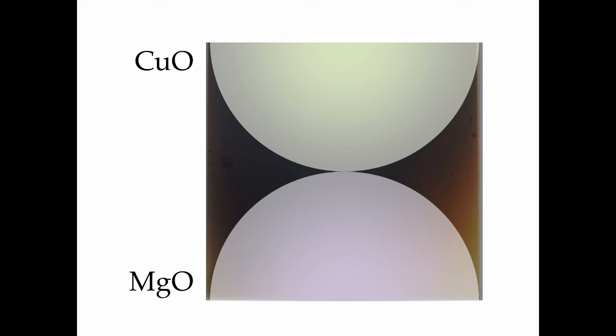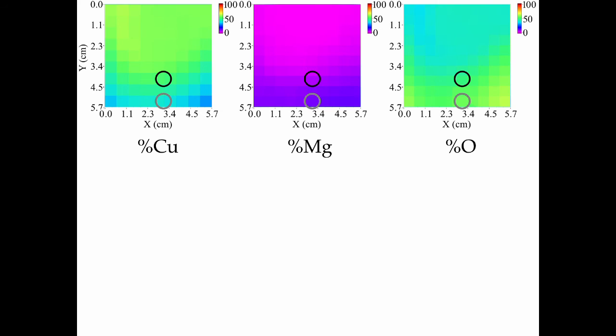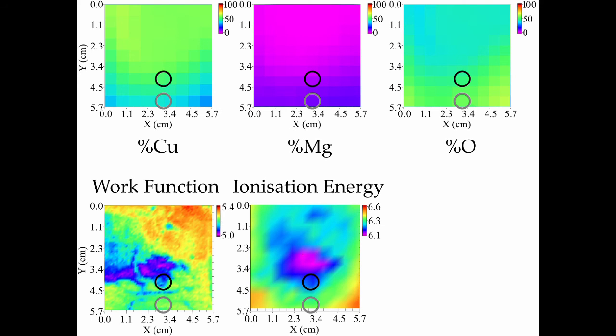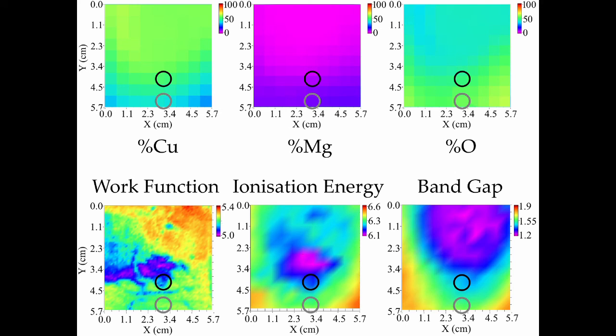To highlight the ability to tune the electronic properties of metal oxide compounds with a spatial variation in the chemical composition, and to demonstrate our analytical capabilities, we return to the copper-magnesium oxide sample that was described earlier, in which the cupric oxide was grown at the top and the magnesium oxide at the bottom. From energy dispersive X-ray spectroscopy, we obtain the chemical composition map, and can see that the copper is rich at the top and the magnesium is rich at the bottom, as expected. The corresponding work function, ionization energy, and band gap maps for this compound are also shown.